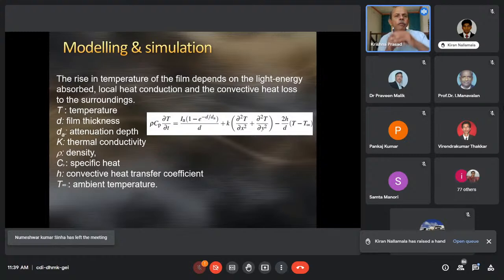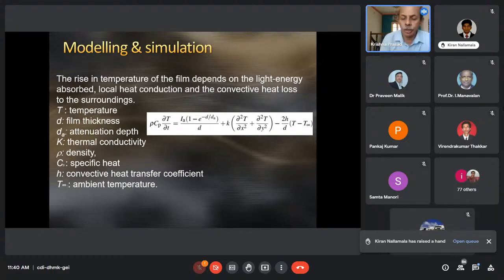And having that kind of a thing, we did both experimental as well as modeling investigations under the system. The modeling has been done by our collaborators at IIT Madras, where currently Divya is a faculty member. These simulations had several parameters which I have listed out here. Our interest was to model these systems considering that the rising temperature of the film depends on the light energy absorbed by the system, the local heat conduction, and the convective heat losses to the surroundings.